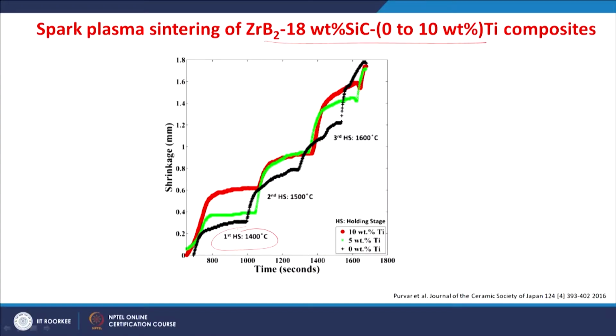In this particular experiment, the spark plasma sintering was done in a 3-stage process. This is called multi-stage spark plasma sintering. So, based on the previous understanding, multi-stage spark plasma sintering was conducted. So, we can see at 1400 there was a holding of 5 minutes, and then at 1500 there was a holding of 5 minutes, and finally at 1600 there was a holding of 5 minutes. So, this is the shrinkage versus time curve for different composites.